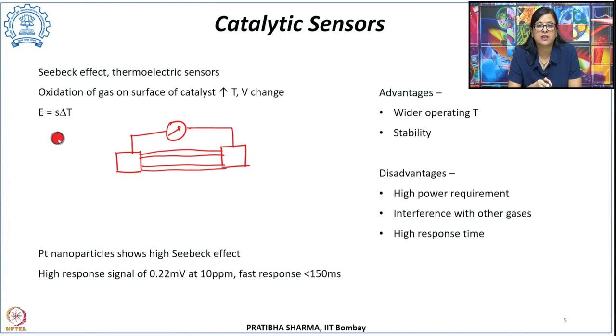Now, there could be different materials, like even the platinum nanoparticles, which have been studied for such type of catalytic sensors, and they have shown a high Seebeck effect. The response signal that we can get from these platinum nanoparticles was observed to be 0.22 millivolt at 10 ppm, and also a faster response of less than 150 milliseconds. So, there are advantages, like a wider operating temperature range and stability, but at the same time the disadvantage is that we require higher power. So, the power requirement in this type of sensor is higher. At the same time, there could be interference with other gases present, and sometimes the response time could be even higher.